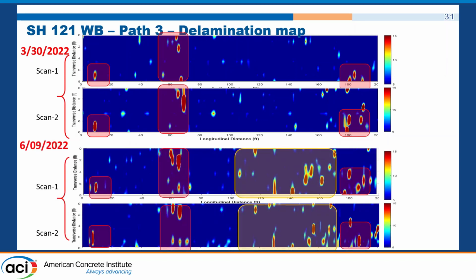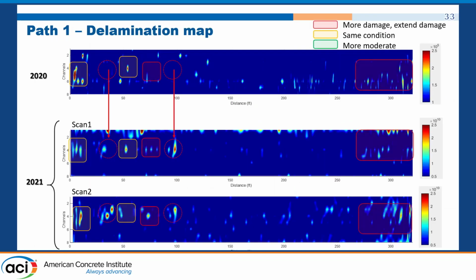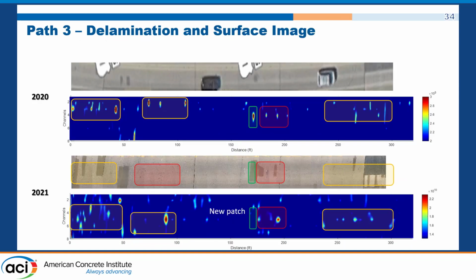And then we scan regularly, sometimes every year, so we can see new delamination coming. This is really unique. They deteriorate very fast here. Many times we accelerate and see that too. For example, this is a very interesting bridge. After a couple of scans, we communicate with the stakeholder, the DOT, and their subcontractor to repair it. When repairing, sometimes we can definitely see the cracks growing and the delamination growing.